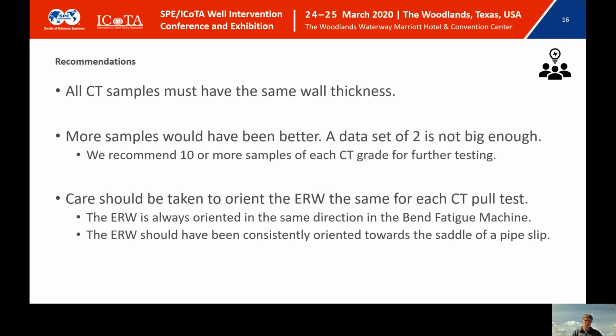So recommendations, if we were to do this again, all coil tubing samples must have the same wall thickness. I think a data set of 2 probably wasn't big enough, but given the time constraints that we had, this is what we were able to procure. If we were to do this again, we'd look for more like 10 samples of each coil tubing grade to get, hopefully, we could start to see some trends emerge.